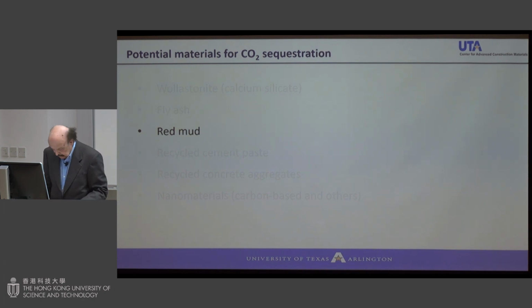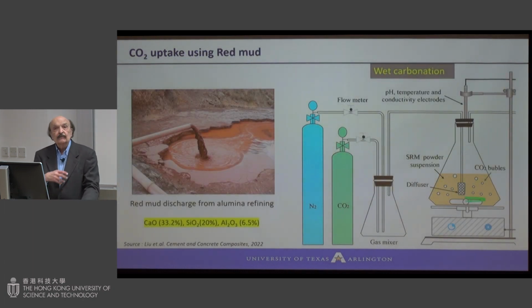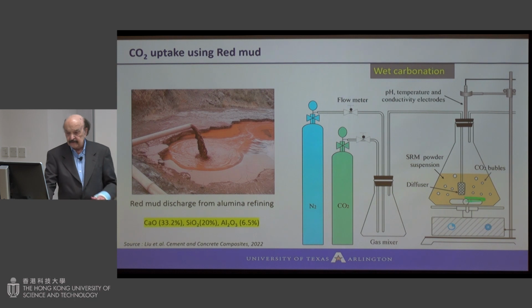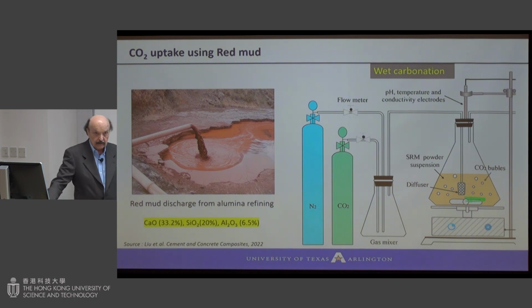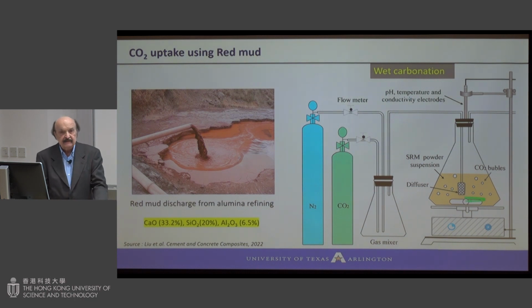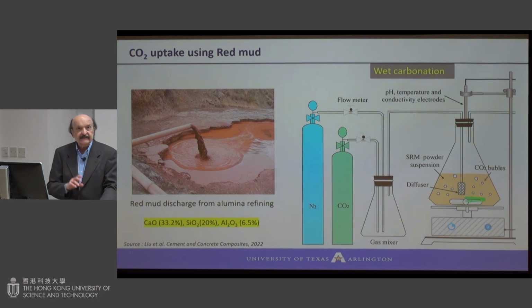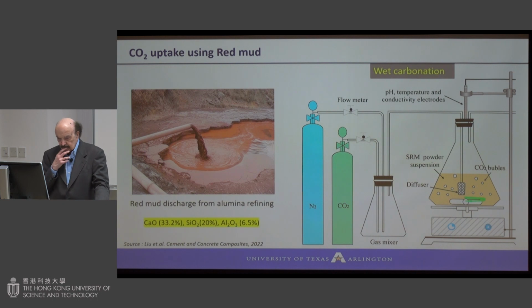Red mud. Now red mud comes from the waste material of alumina. Professor Lee, the Jinan people tell me that Shandong has a large amount of waste red mud, and in the US, in the western part of the US. So what do you do with this red mud as a waste material? This is the work done at Hunan University. Red mud has lime, silica, and alumina. So what is done is you carbonate red mud. This is a wet carbonation, and then dry it and use it as a powder.